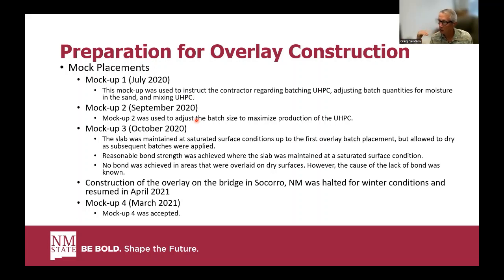Basically, they want to mix as large a quantity of material as they can. And it's just a difficult material to mix. You've got to have more energy per unit volume than with pretty much any other material that you might try to mix, especially once you get the steel fibers in there. So basically we spent that mock placement dealing with the contractor, trying to get their mixer to mix a larger batch of concrete than it was capable of. So we just kept downsizing the batch until they actually got something that would mix up.